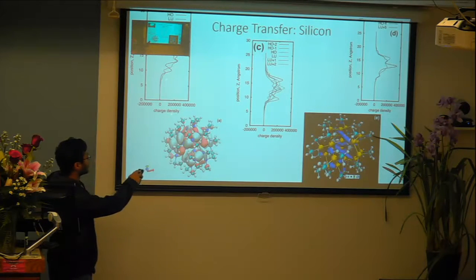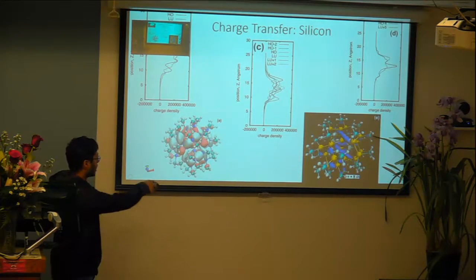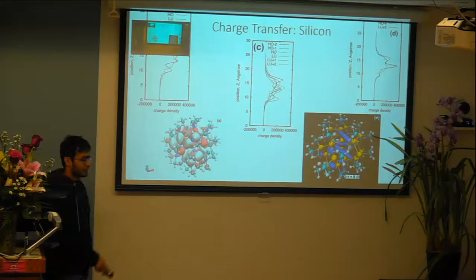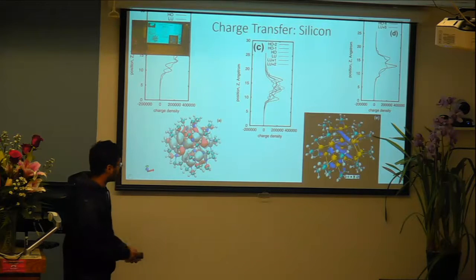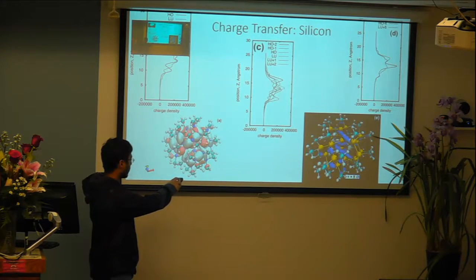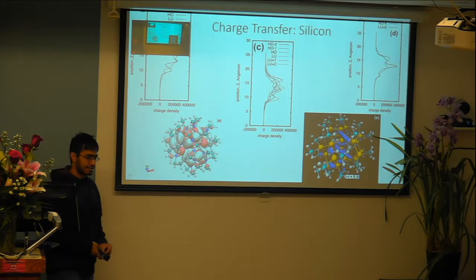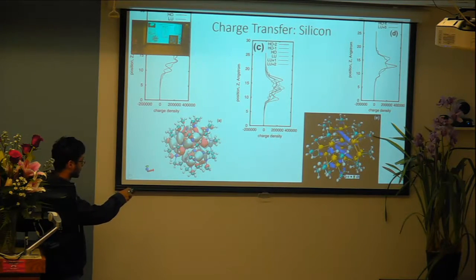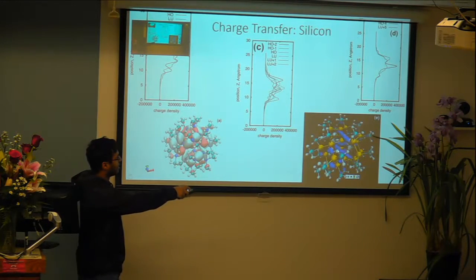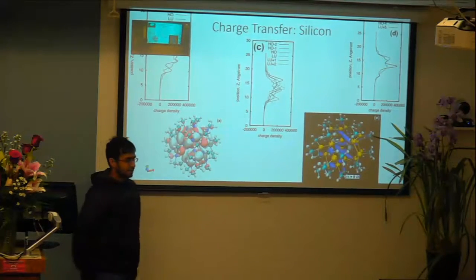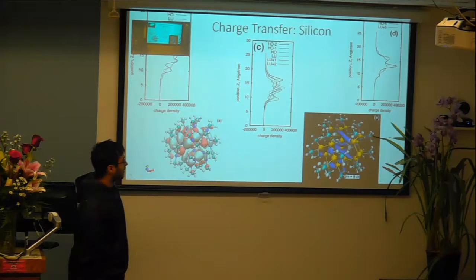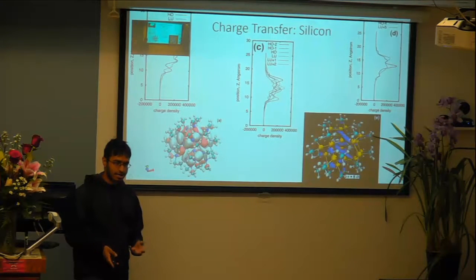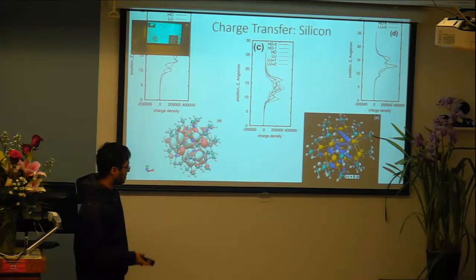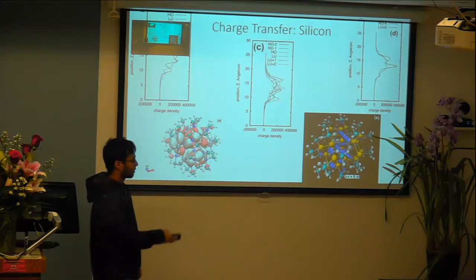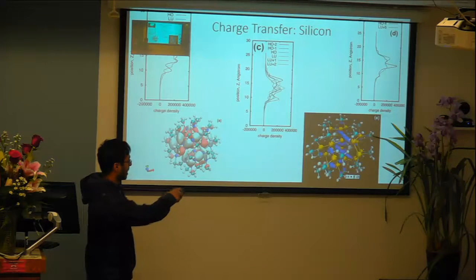And here on this slide, you can see a couple of charge transfer plots. So on this left-hand side, these are the charge transfer plots for the HOMO and LUMO orbitals. And then on this model on the lower left-hand side, the HOMO orbital is represented by pink, and the LUMO orbital is represented by gray. And on the right-hand side, we see that there is some charge transfer between HOMO -4 and LUMO +5. However, there still is not too much. So further work could be done in order to actually characterize different morphologies and different oxidations and determine where the most charge transfer will actually occur, for which models they will actually occur in.